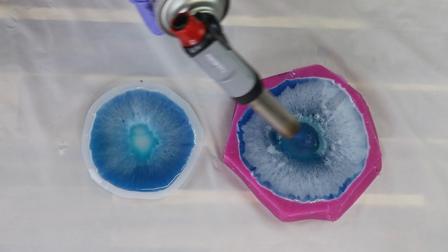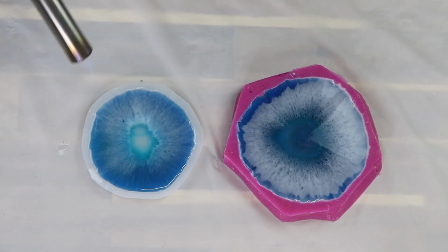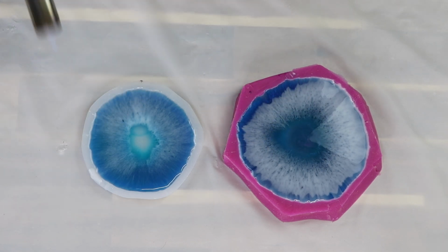So you can use a blowtorch, a heat gun. They're both really helpful items, but they will only get the surface. So if you've got a ton of bubbles in your mixture and you pour it straight in, you're only going to be able to get the bubbles that are on the surface off. So it's really good to just give that a little bit of time to sit there, rest, let them all come up, get rid of them, and then pour.